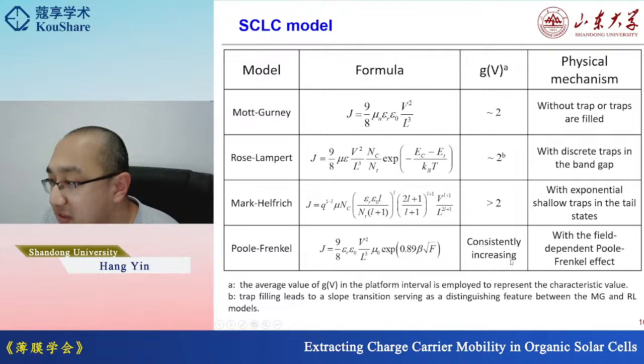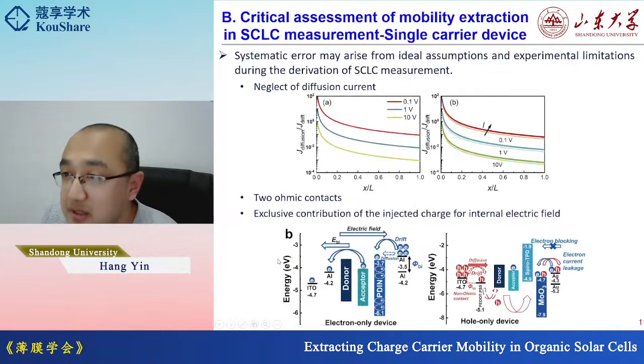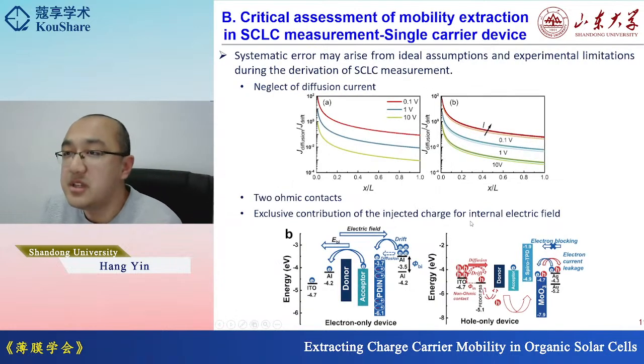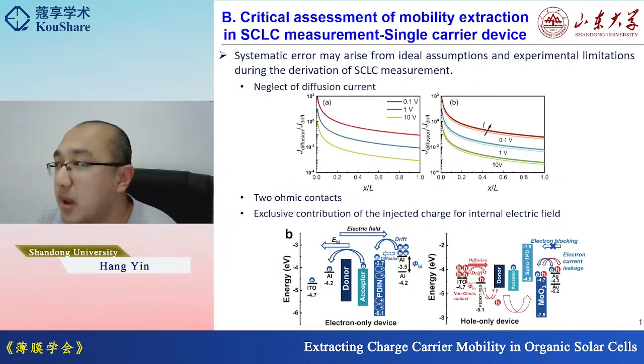But we can see the G value is consistently increased. So sometimes we can get a huge error if we only consider the PF effects instead of the others. So therefore, how can we address this problem? Because for the standard SCLC model, there are a lot of ideal assumptions and experimental limitations during the SCLC measurement.